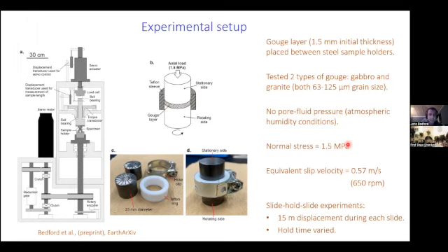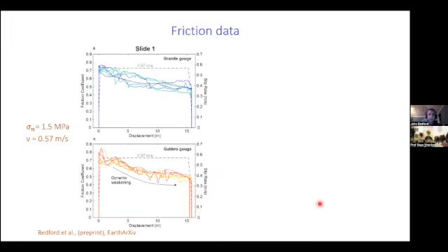And in these experiments, what we did is essentially slide-hold-slide experiments where they were sheared at high velocity for 15 meters of displacement, and then we held them for various amounts of time and then re-sheared them to see how the stress evolved. And you can see the data from the first sliding event in the experiment. Here we've got the granite gouge on top and the gabbro gouge below, and we see that both gouges have a peak friction of between 0.7 and 0.8, and then that decreases down to around 0.5 by the end of the first sliding event,